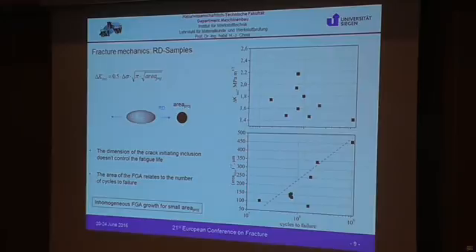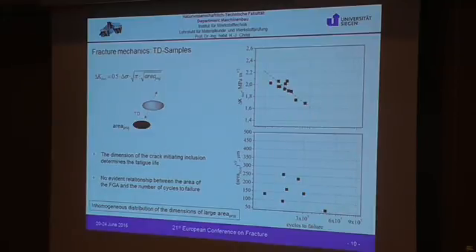The area of the FGA is larger for a higher number of cycles to failure, which is in agreement with the literature, because the FGA formation takes the highest amount of the fatigue life. For the TD samples, however, the projected area of the inclusions is much larger, as well as the delta K calculated at these inclusions, and we find a very good correlation between delta K and the number of cycles to failure. In this case, the FGA area doesn't correlate very well with the number of cycles to failure, because the scatter of the inclusion size has a larger influence on the fatigue life and occupies the larger area of the FGA. So the inhomogeneous distribution of these inclusions is responsible for the large scatter of the fatigue results.